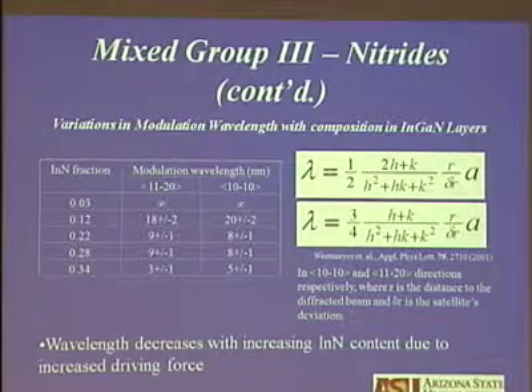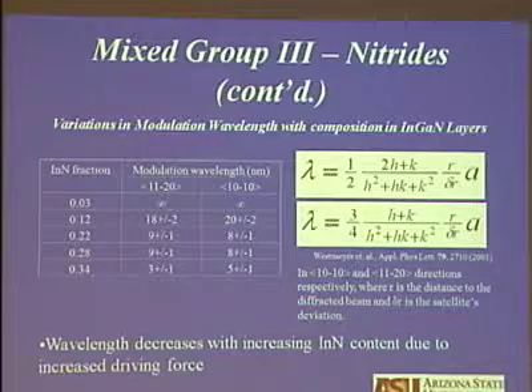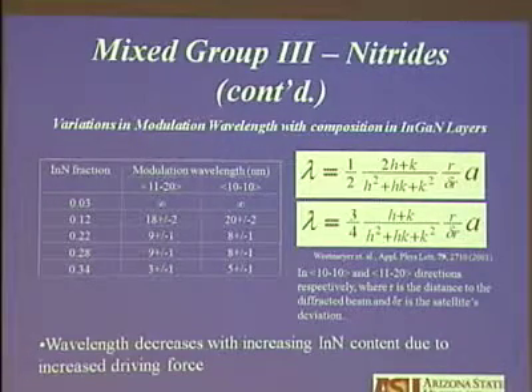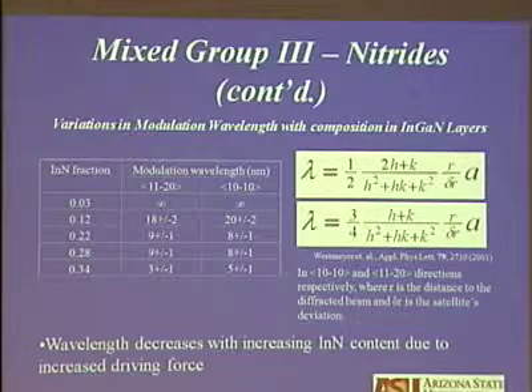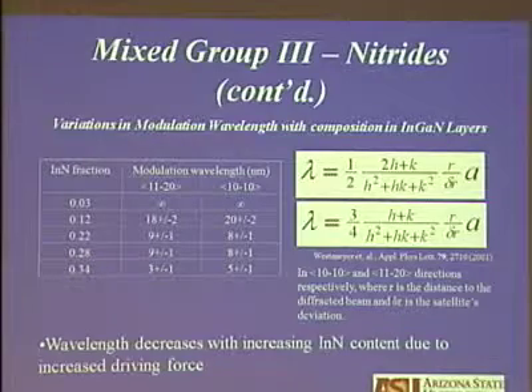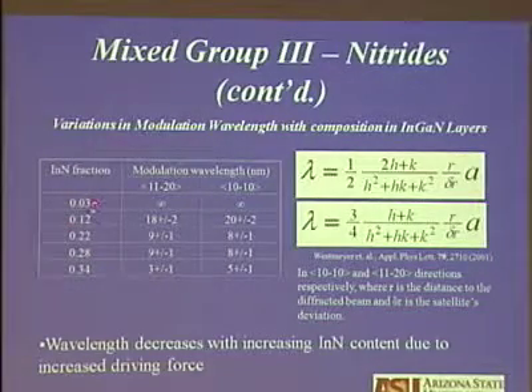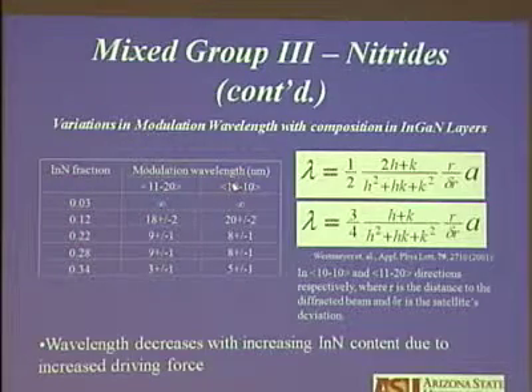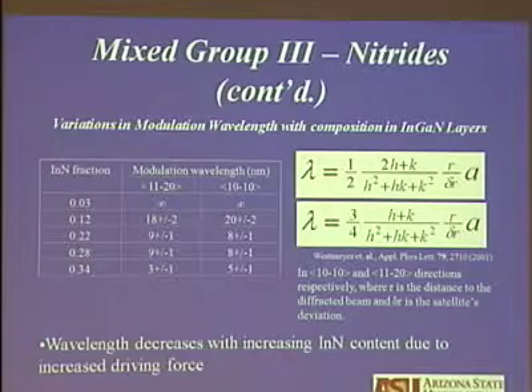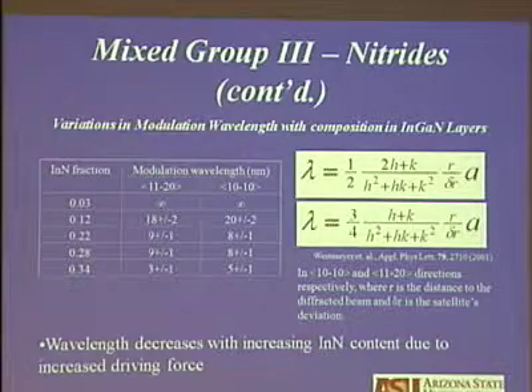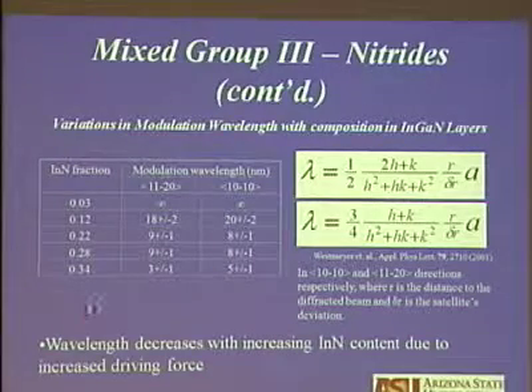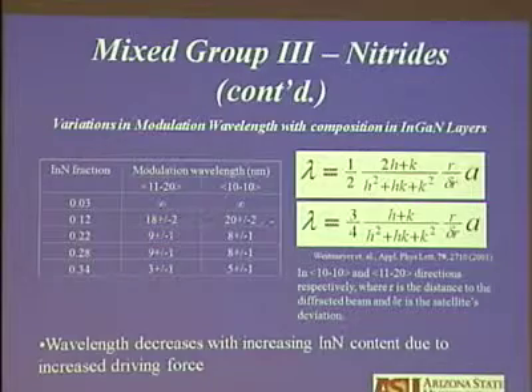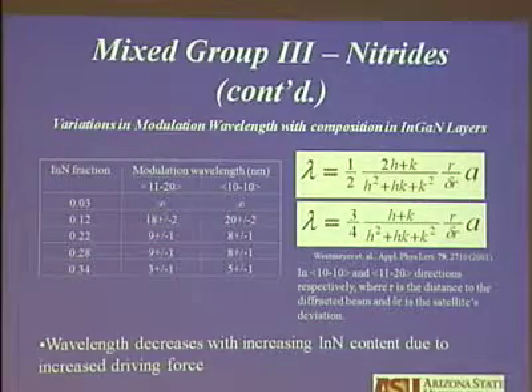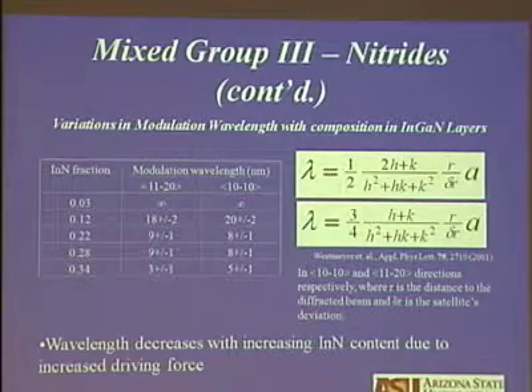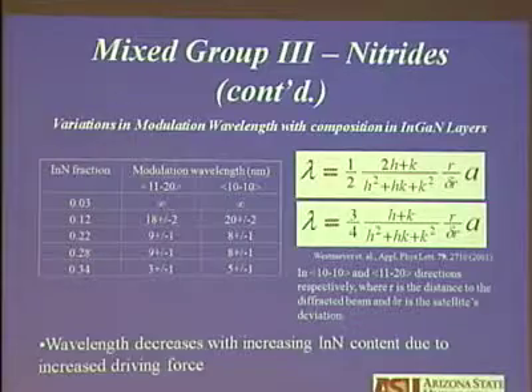Luckily, we have a growth system ourselves. Otherwise, it's very difficult to do these studies. When I joined ASU in '97, I made sure we had a growth system to ourselves in the materials program. When you grow with a small fraction of indium, the wavelength along these directions, along which direction the phase separation occurs, is infinity. That means there is no phase separation. As you increase the composition, the wavelength decreases as the indium content increases. And that's the formula we use to determine the wavelength. The reason is that the driving force for phase separation increases as you increase the indium content in your layer.